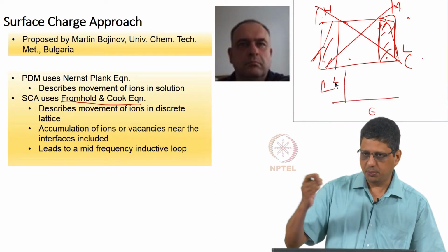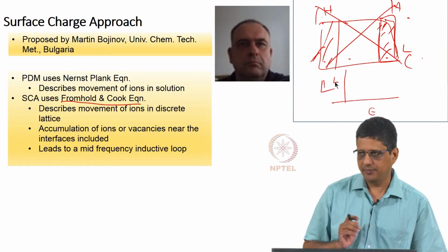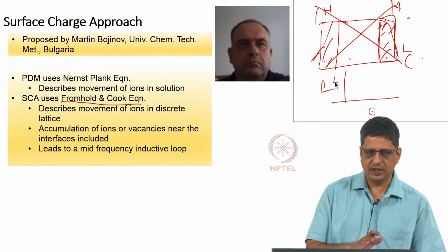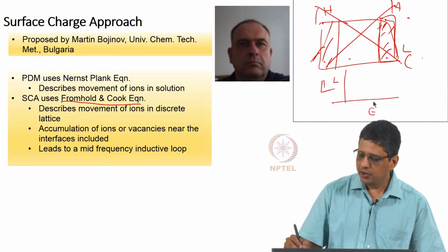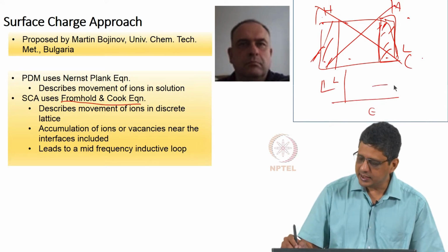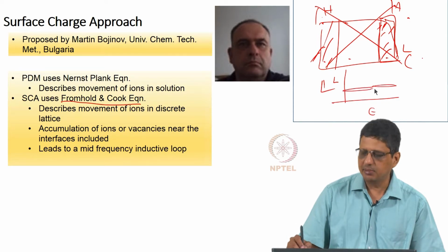If you go to larger potential, you will expect a thicker oxide in the passivation region. So, if I apply a sinusoidal potential, I am increasing, coming back to this, decreasing and coming back to this. I can also expect the film thickness will increase, come back to the original, decrease and come back to the original, provided the potential variation happens at a very slow rate.